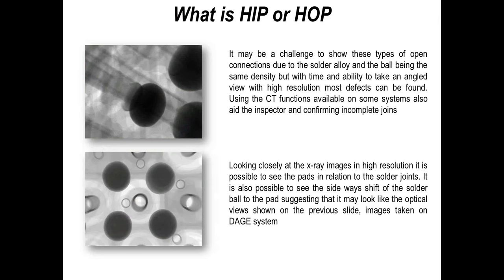Now, you can see the same sort of things with high-end X-ray machines and certainly CT, if you have that capability. And in these examples, basically what I've done is moved the sample around within the X-ray chamber. And you can actually see the shape change. Now, if you just look straight down through the X-ray, straight down through the ball onto the pad, quite often you can't see it. But if you're able to orientate the board or the head, you can see it if you take a bit of time. And certainly, obviously, this is more non-destructive than the dye and pry I mentioned earlier.